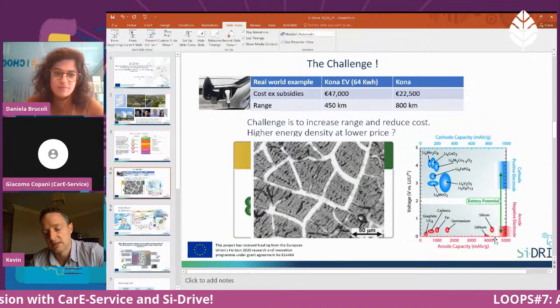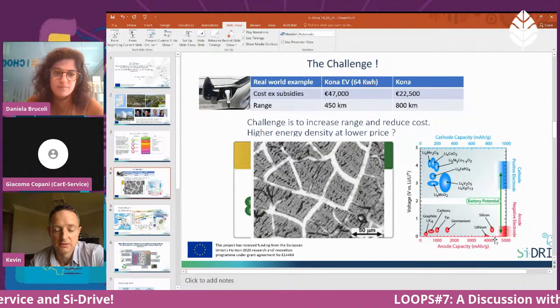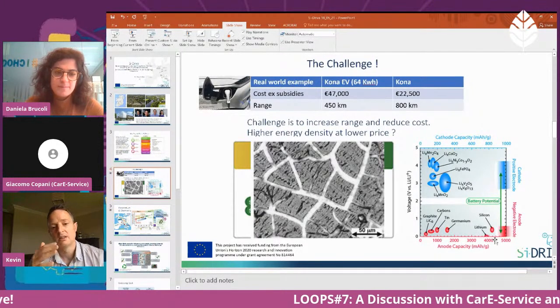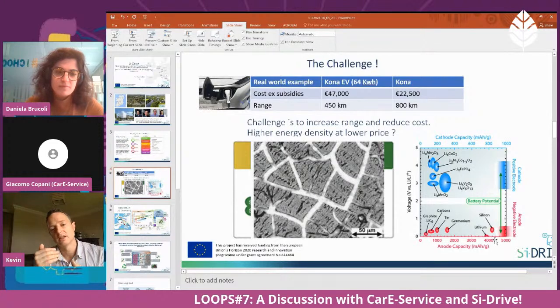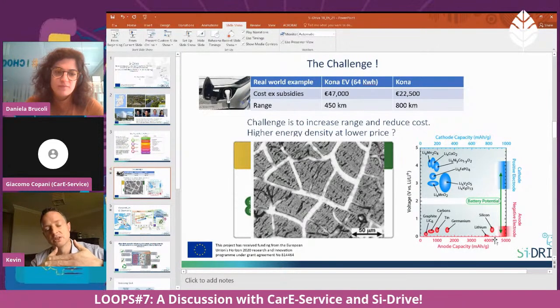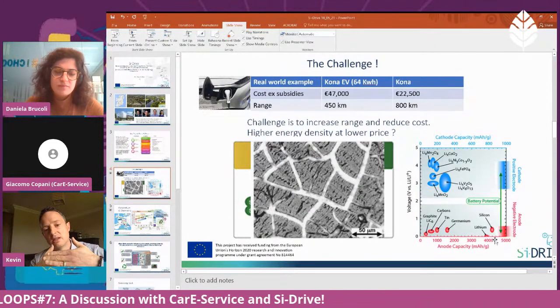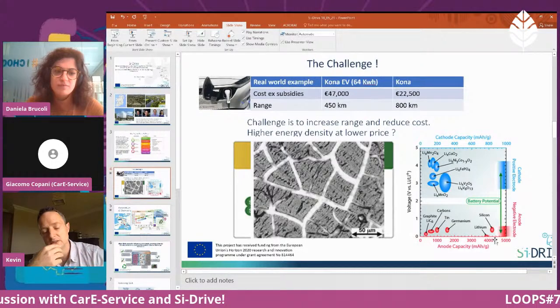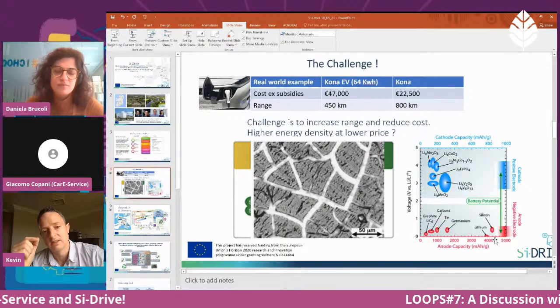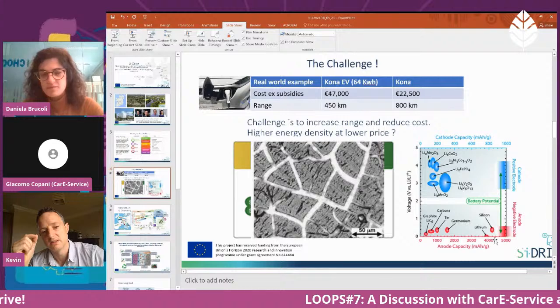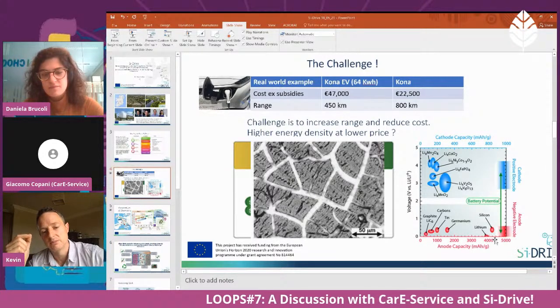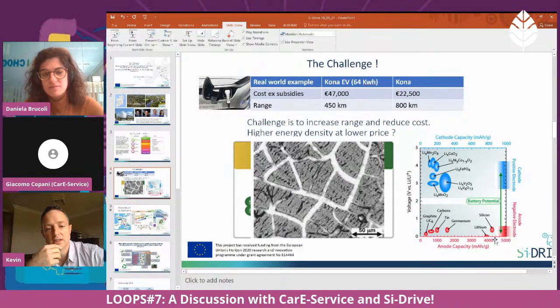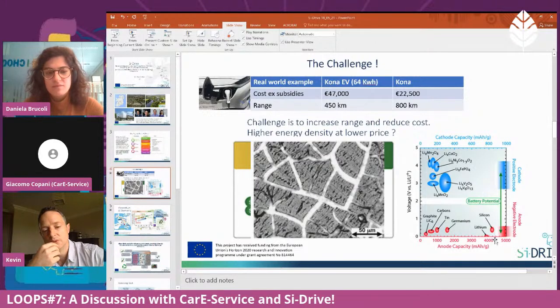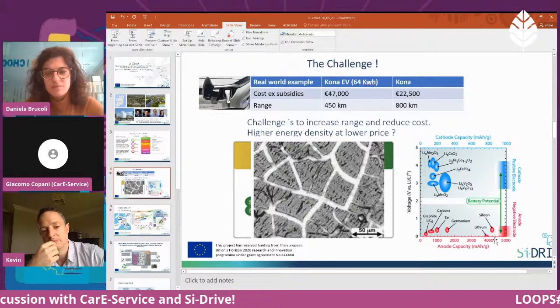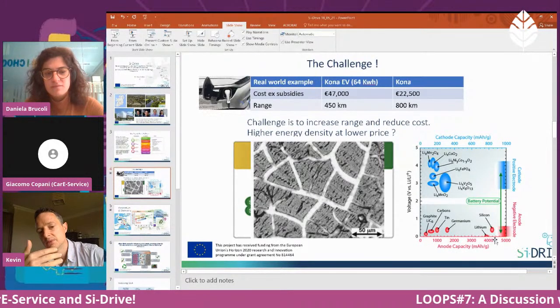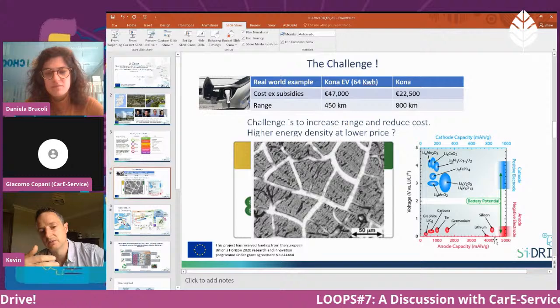the process by which silicon uptakes lithium is different to graphite. With graphite, you essentially have sheets of carbon, your hexagonal sheets, and your lithium intercalates between those sheets. Whereas with silicon, it's an alloying process, and what happens is that you get 4.4 lithiums for every silicon atom once you cycle with lithium, and so versus a 10% volume increase with graphite,